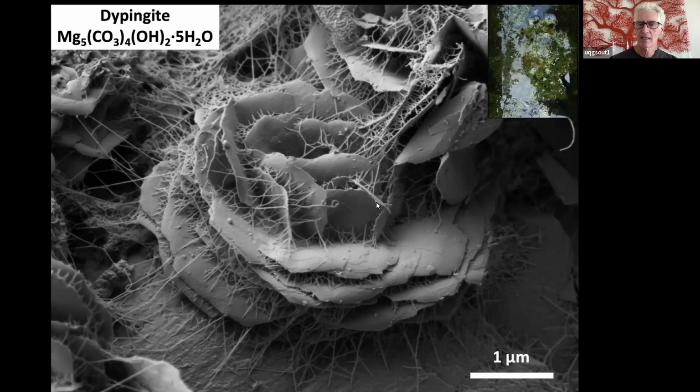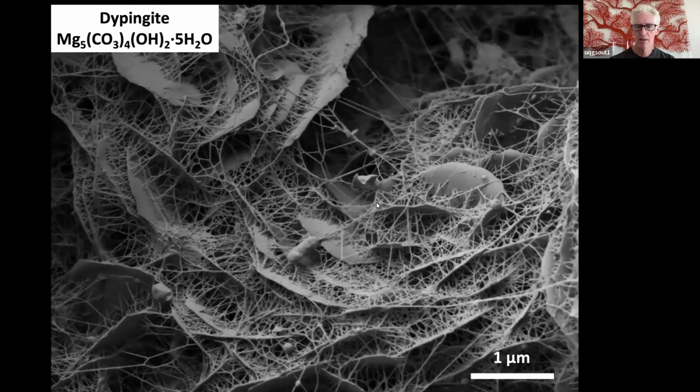And so it's this gel that has a net negative charge that brings in cations like calcium and magnesium, and then the photosynthetic activity, which shifts the chemistry towards minerals that are forming. Probably one of the most interesting images that Janine McCutcheon produced is shown here, where we've got a massive amount of exopolymer that's nucleating the growth of the minerals. And so I would argue here that what we're looking at is a biogenic mineral. It's the EPS by the bacteria that are nucleating the growth of these materials.